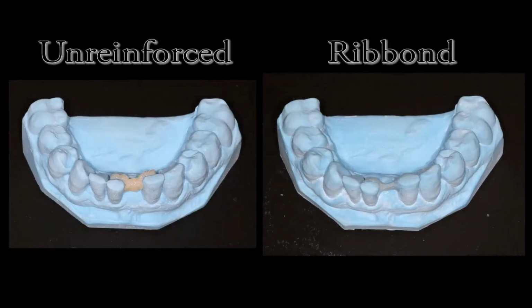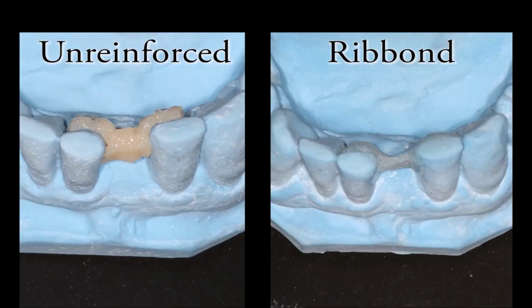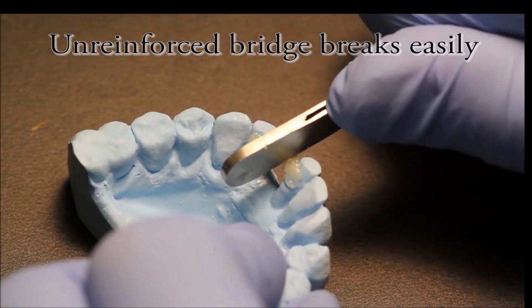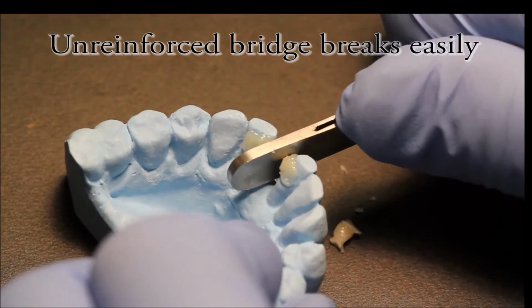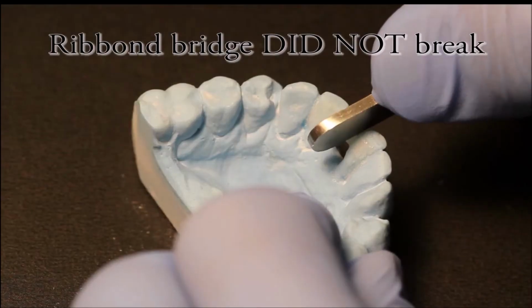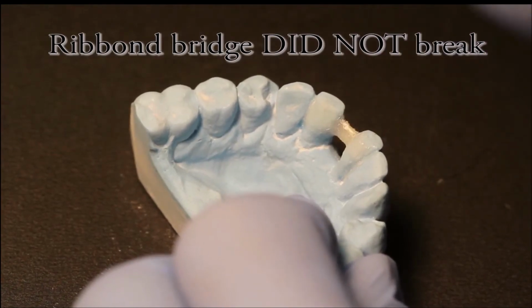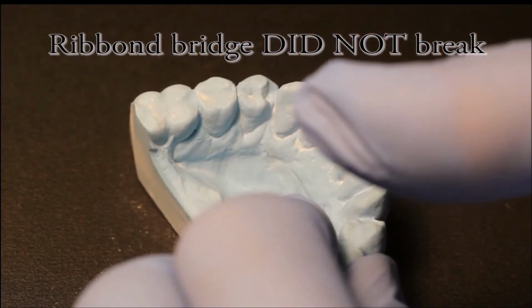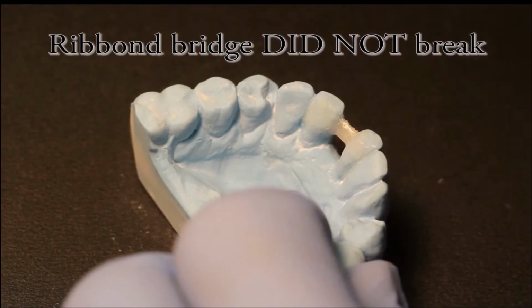You can see how Ribbond prevents fracture failures in these videos. Shown here is a model of an unreinforced composite resin bridge framework and a Ribbond reinforced bridge framework. To emphasize the effectiveness of the Ribbond, we made the composite bridge framework significantly thicker than the Ribbond bridge framework. The unreinforced composite broke quickly and without much force. The Ribbond reinforced bridge did not break after significantly more force was applied to it. As you can see, Ribbond prevents fracture failures.